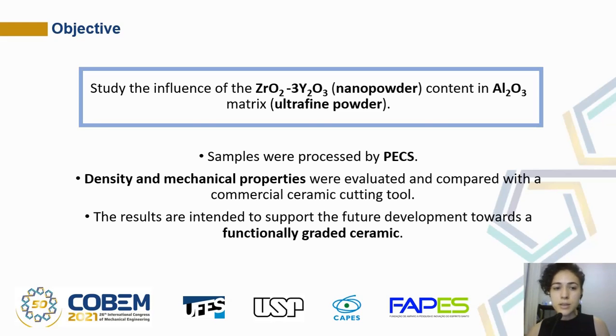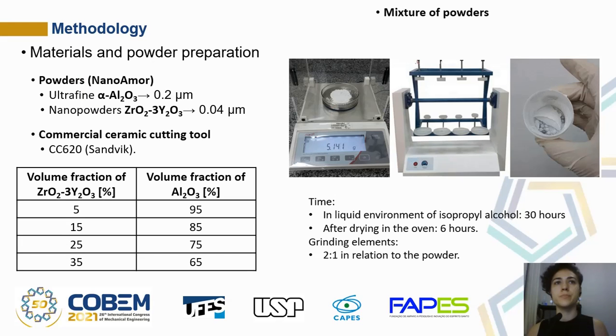The density and mechanical properties were evaluated and compared with a commercial ceramic cutting tool, and the results are intended to support the future development towards a functionally graded material. The materials used were ultrafine alpha alumina powder, nanopowder of zirconia stabilized with yttria, both from NanoAmor, and the commercial ceramic cutting tool CC620 from Sandvik.